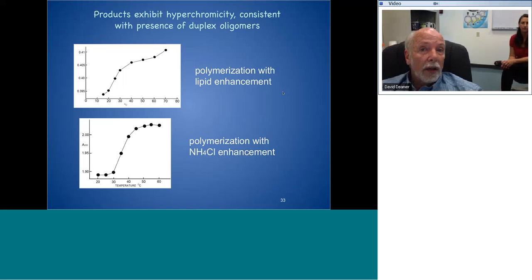Okay, whatever the products are, they have hyperchromicity. There's a couple of experiments, one with lipid and one with ammonium chloride enhancement. This level of hyperchromicity in this TM, transition temperature range, is equivalent to about a 15-mer. So when you see this kind of melting curve in RNA, it's as though there are regions in those much longer strands that seem to have a little bit of duplex structure that does in fact melt and show hyperchromicity as expected.